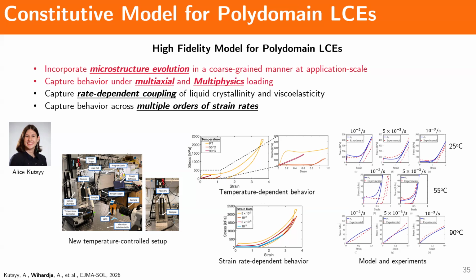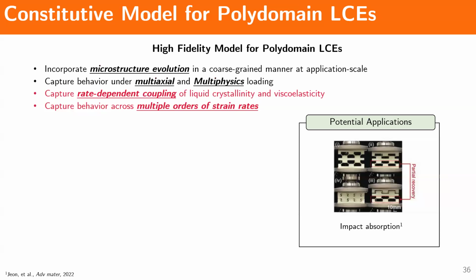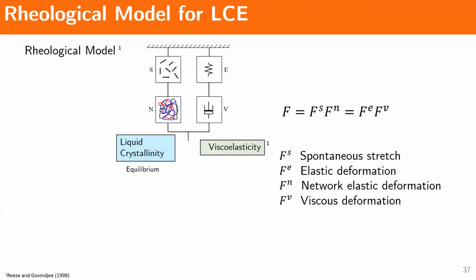So now I'm going to move on and look at this behavior under high strain rate loading, because we're motivated by the impact absorption applications for these materials. We want to be able to capture a rate-dependent coupling between the liquid crystals and the rubber elasticity. To do that, we borrow theory from large deformation viscoelasticity, which was actually developed by Sanjay here. So we borrow the theory that he developed, and we consider the following rheological model for our LCE, where we have two branches.